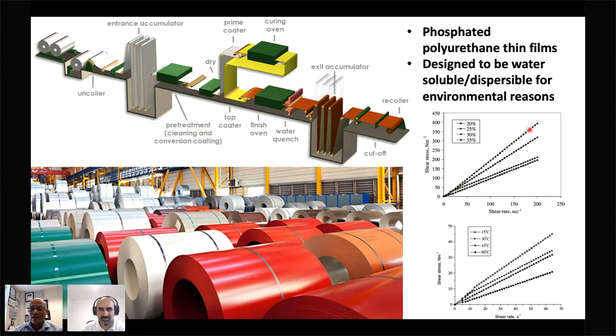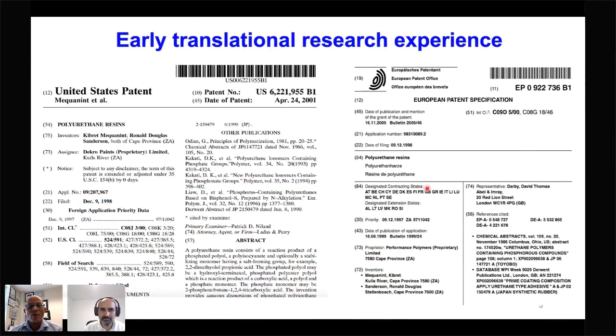We have done a lot of studies, as you would expect. I will not be able to go through most of it, but rheological characterization was very important because the coating applicator here has a number of rollers, and these rollers exert a certain amount of shear. And so we have to look at whether the polymer was Newtonian or non-Newtonian or shear thinning or shear thickening, and then we have done quite a lot of studies. So that was basically the beginning of my involvement in translational research, and of course that led to a series of patents, as you can see in here.